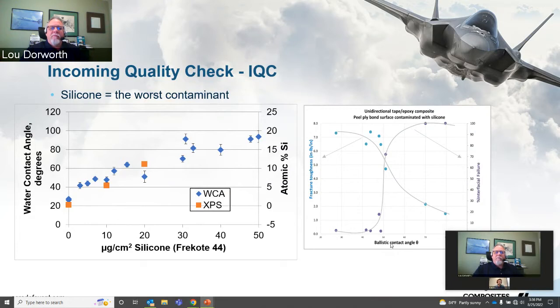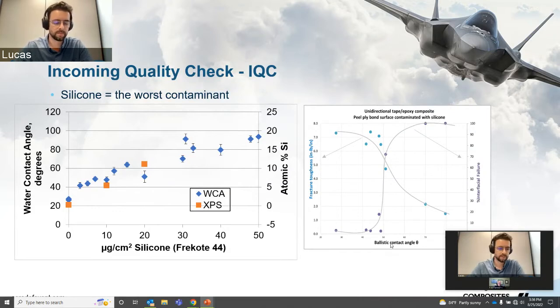We're calling out Frekote 44 here just because this is what we used in the experiment, because it's easy to apply for the experiment. In this case, we're just trying to understand the sensitivity of the technique to contamination, and what's the contaminant that we really care the most about? It's actually usually not hydrocarbon based contaminants. It's almost always silicones.